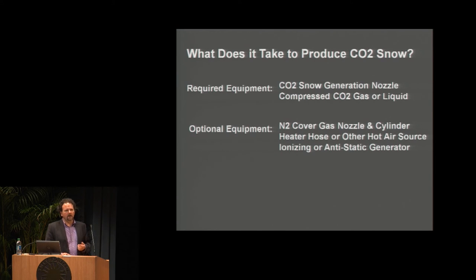Robert talked a little bit about that. You can use a dry nitrogen cover gas. This is about controlling your moisture. You can heat the gas, or you can have warmed air. You can also address static buildup on the surface. Anytime you have small particles moving very quickly over a surface, there's a high likelihood you're going to generate a static charge. The unit you'll see upstairs, and I'll talk about it in a moment, is a Cadillac version. It has an inline anti-static generator that generates across the gas stream that helps you dissipate the static on the surface.